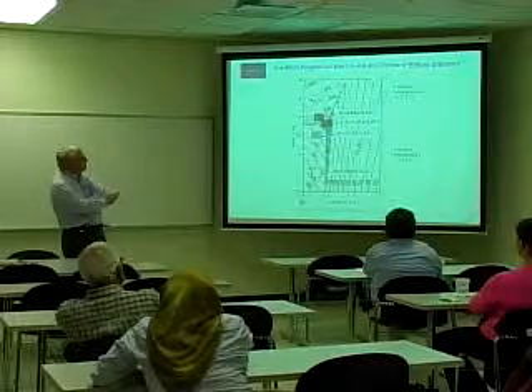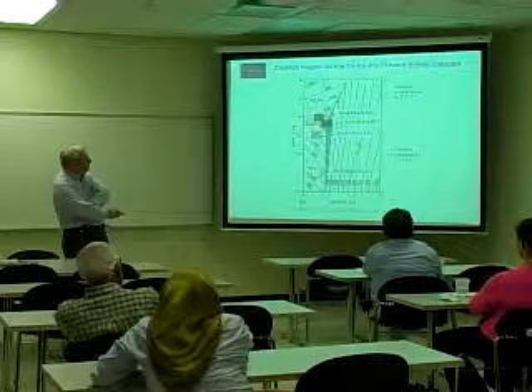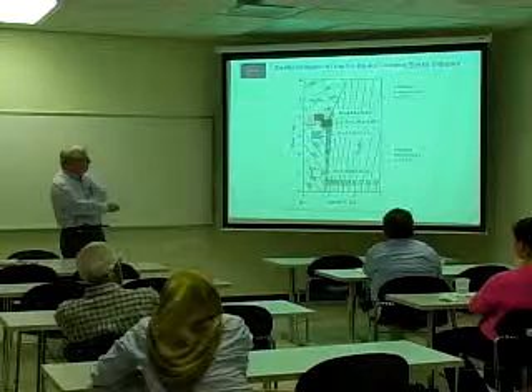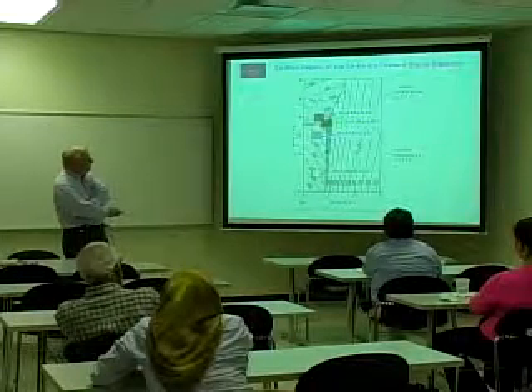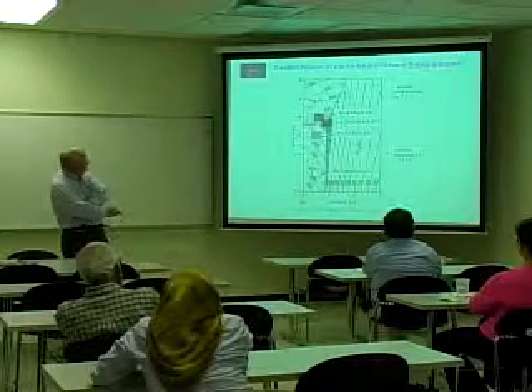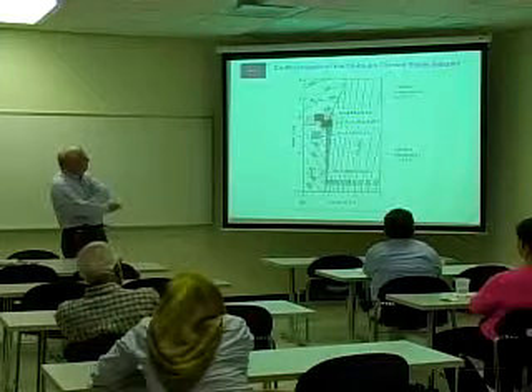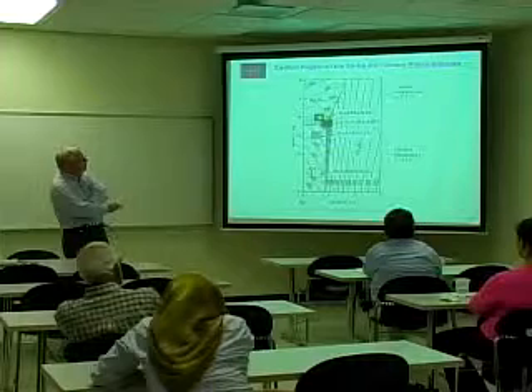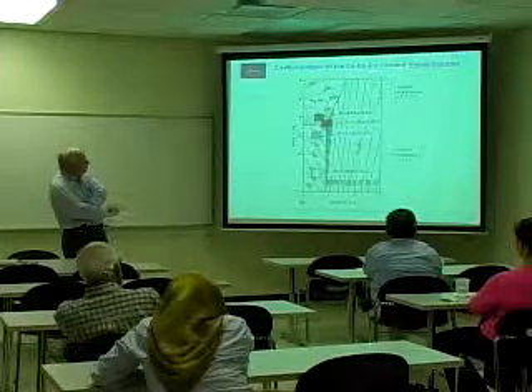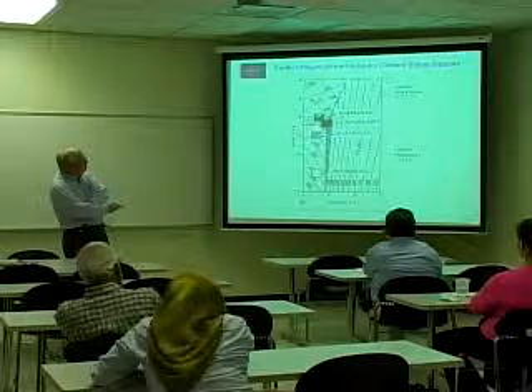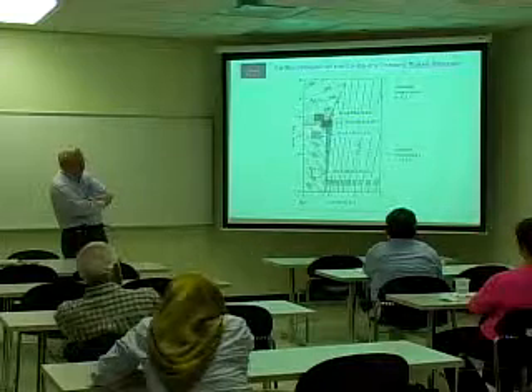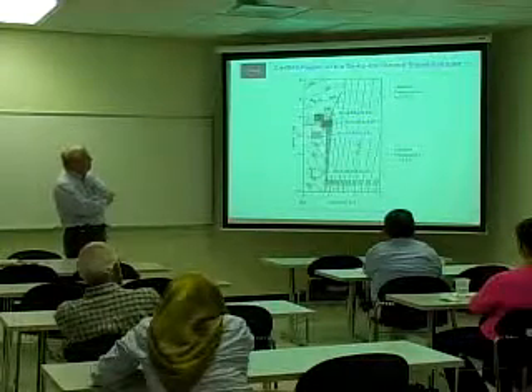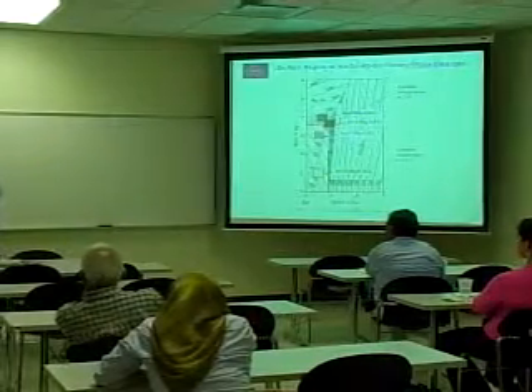My point of this slide is there are two things. One is, for example, SAC 105 is one of the solders that people are using for more robustness in vibration, for example. This one, you can see you have to heat to a fairly high temperature, probably about 226, before it becomes a liquid. If you make a SAC alloy solder that's way off on either side of this tin-rich segment, you can see you actually have to increase the temperature to turn it into a liquid by quite a bit. The other part of this is when you buy a SAC 305, it isn't necessarily 3% and 0.5%. It's probably close to that, but there's some manufacturing variability. So you have to build tolerance into your process. You can't just believe these numbers straight away.